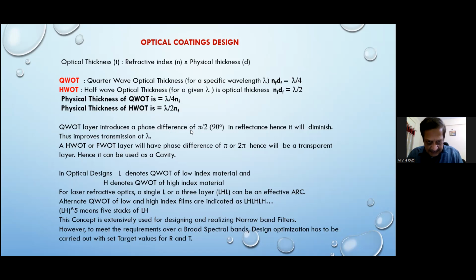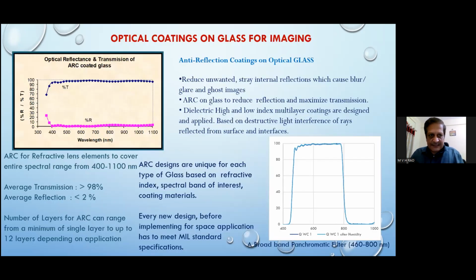So whenever there is a quarter wave optical thickness, the phase difference is 90 degrees, so there will be a destructive interference. When it is a half wave optical thickness, consider the two rays, one reflected from the top layer and another from the next layer. The two light waves reflected from these two locations interfere with each other. If the phase difference is pi or 2 pi, it will be constructive. If it is pi by 2, it will be destructive. So basically, these optical interference techniques are used to design the films. And I'll quickly go through. This is one of a very broad band anti-reflection coating covering from 400 to 1100 nanometers, NIR.